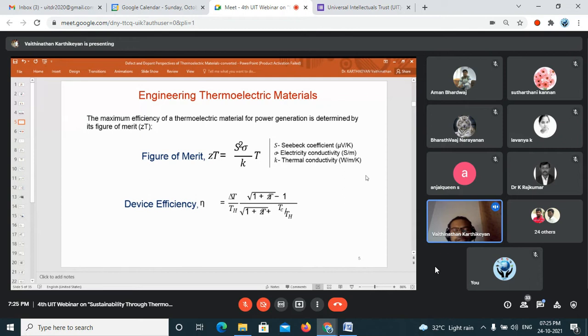Most of the thermoelectric materials are semiconducting materials with narrow bandgap. And the figure of merit is determined by these three parameters: the Seebeck coefficient, electrical conductivity, and thermal conductivity. The Seebeck coefficient squared times the electrical conductivity we call the power factor, as I highlighted here, and K is the thermal conductivity.